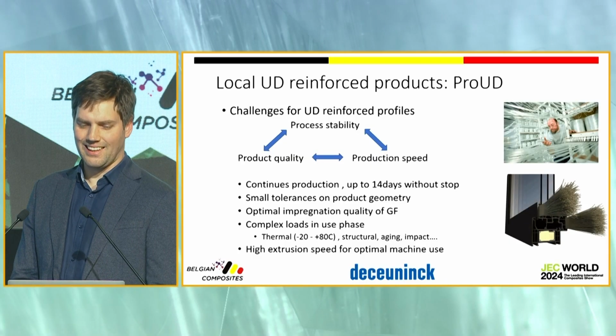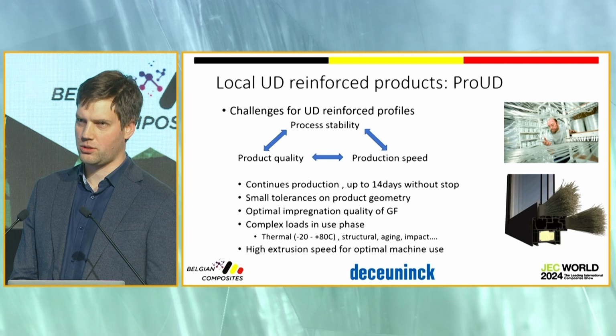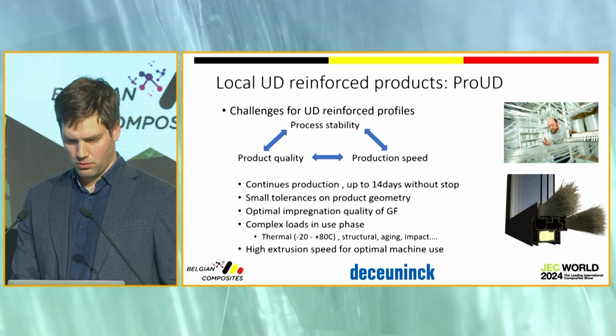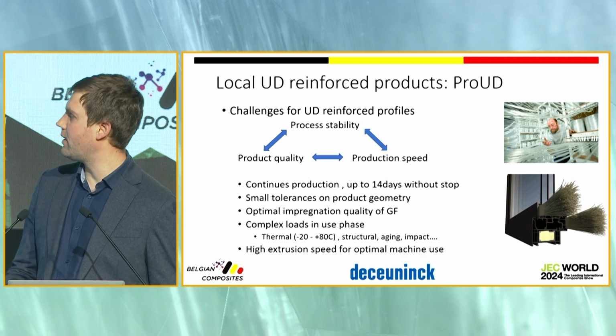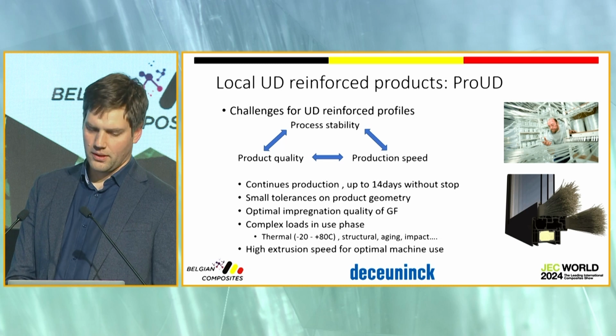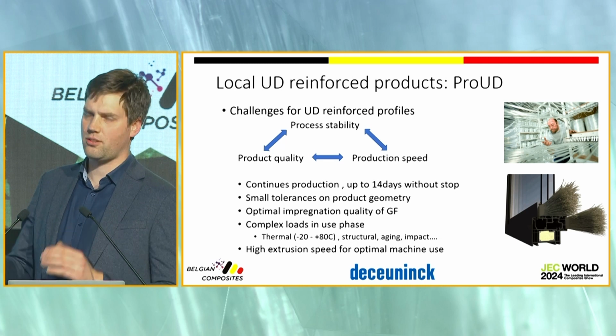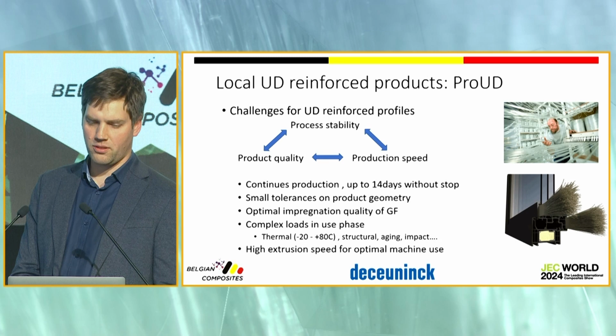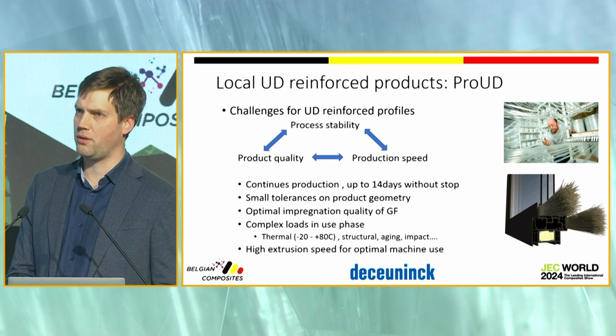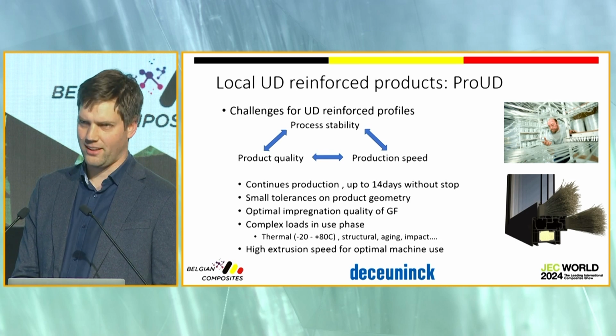Well, we want to have at least a 14-day production run without stopping. So this, I don't know if you can see it, but the window profile is on the screen. The glass fibers are on both sides of the PVC profile, and the production of this PVC profile runs for 14 days without any stop.